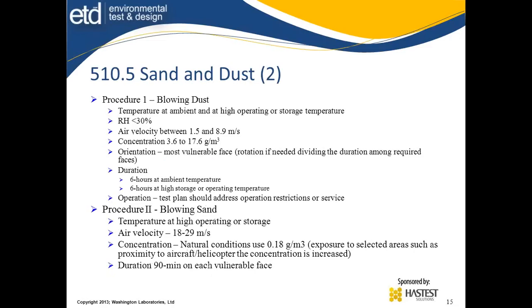The blowing dust is procedure 1: the temperature at ambient with high operating or storage temperature, and at a high operating temperature with a humidity below 30%. This prevents you from clogging up the dust particles. The air velocity is stated, it's pretty wide, along with the concentration. You've got a lot of variables in dealing with that situation.